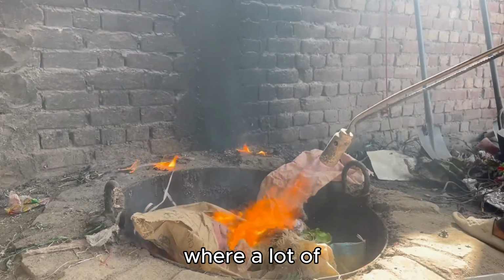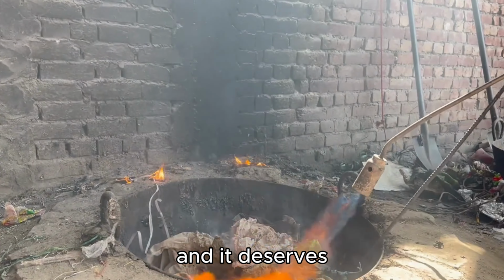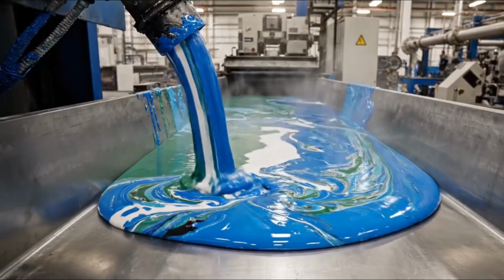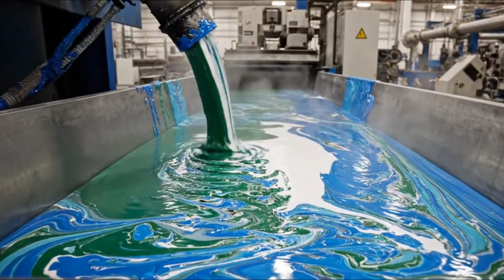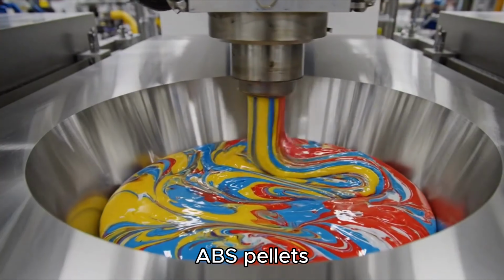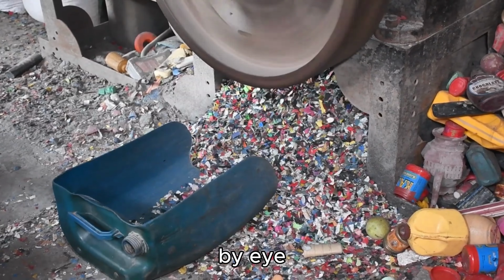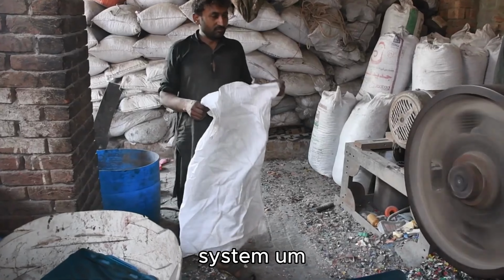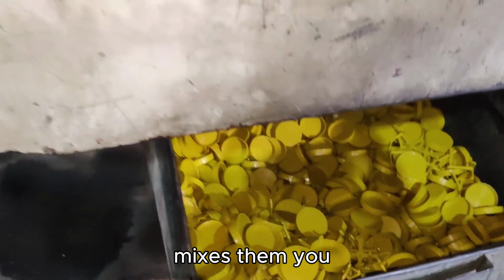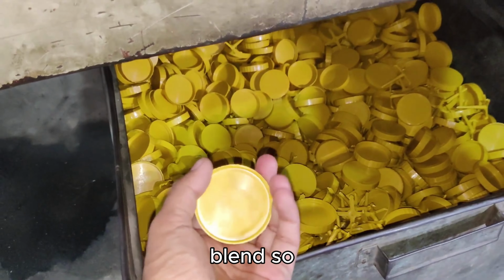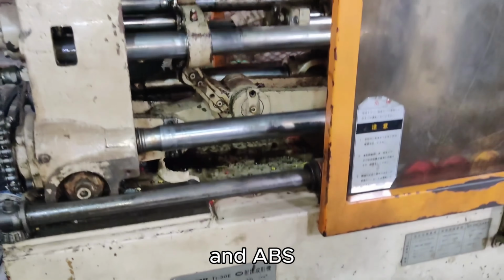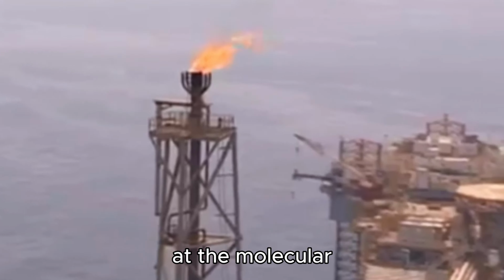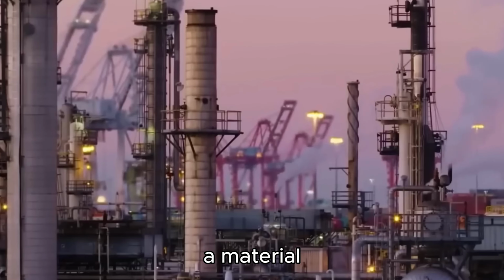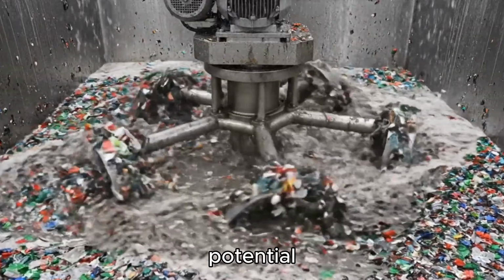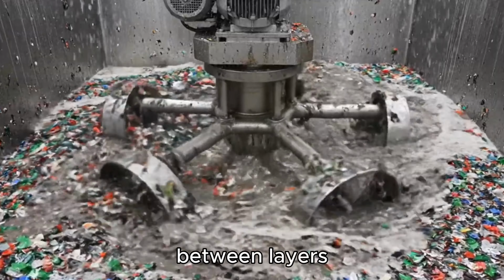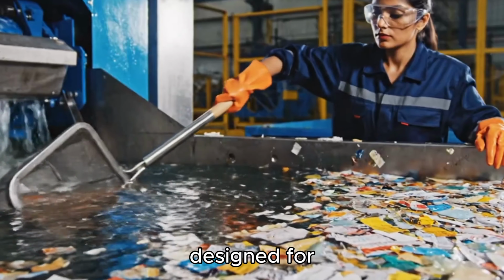That separation issue is where a lot of facilities quietly fail, and it deserves a direct look. Plastic resins look similar. Black polypropylene pellets and black ABS pellets are nearly indistinguishable by eye. If a regrind collection system even occasionally mixes them, you end up with a contaminated blend. When polypropylene and ABS are melted together, they don't bond at the molecular level. The result is a material with degraded mechanical properties, potential delamination between layers, and failure modes that no engineer designed for.